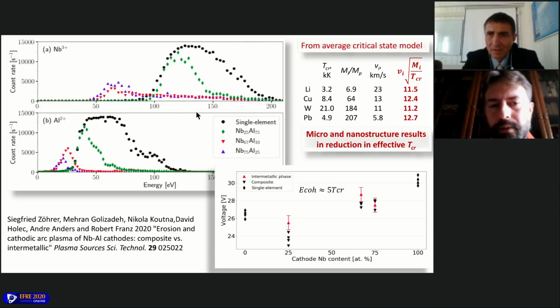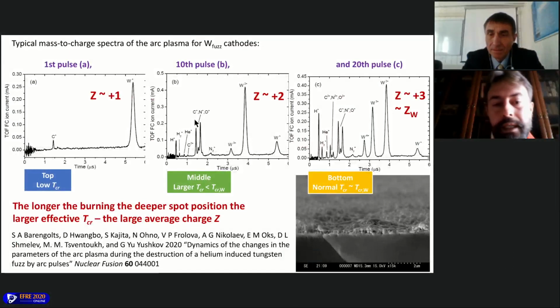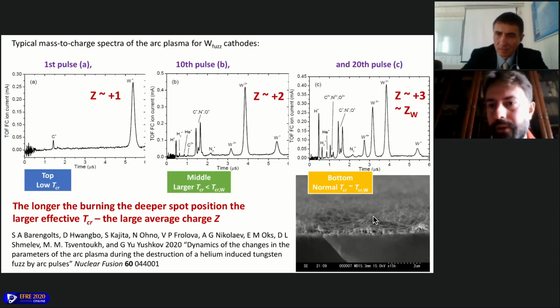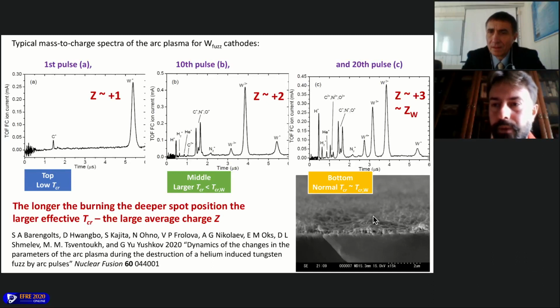So maybe it is not strictly an extension of liquid jets, because in fact for the tungsten nanowires we have almost no liquid metal at the surface until it burns to the bottom. So a few microns of this layer provides effective burning of arc without liquid metals. But probably we can use some extension of this model of critical state with effective average state for some real materials. It means that we can derive some more general model.